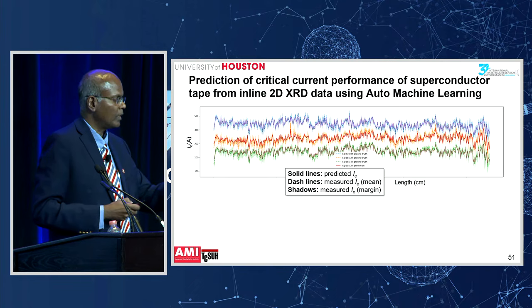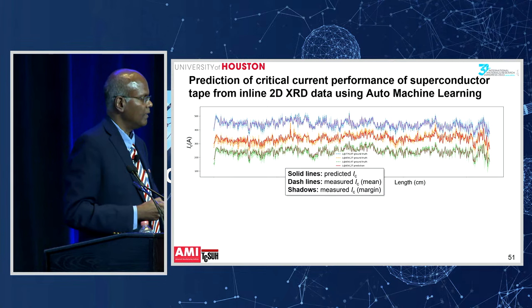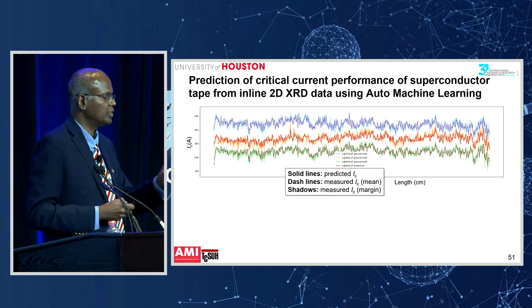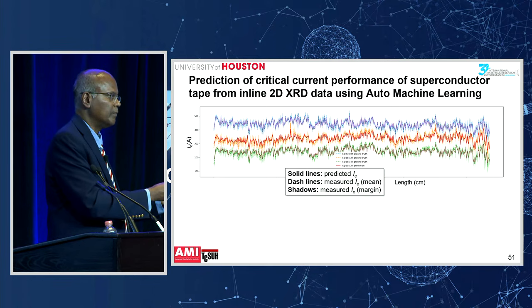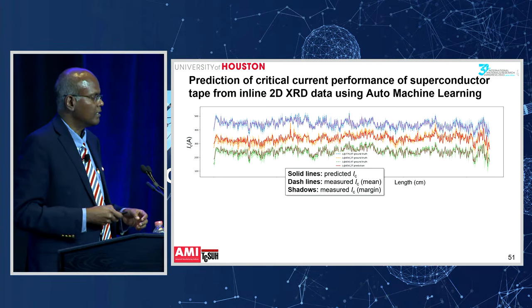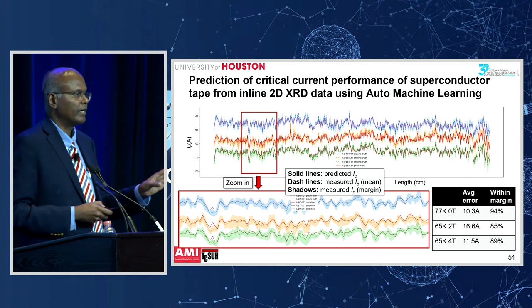The dashed lines are the critical current actually measured at three different conditions. And then the solid lines are what's predicted by the machine learning method. We used a set to train the machine learning algorithm and then used that to predict the rest of the tape. And you can see there's a pretty good prediction from the X-ray diffraction data. You can actually predict what the critical current is going to be.